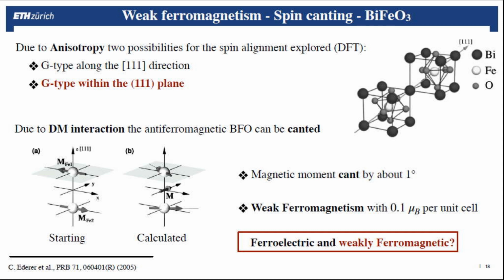Why is this important? Because I told you that for applications of multiferroics, one would look for a ferromagnetic and ferroelectric system to switch or to have coupling between them. And I told you that bismuth ferrite was ferroelectric, so that's very good, but antiferromagnetic.